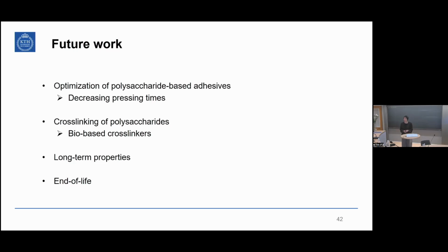For future work, it would be interesting to optimize these polysaccharide-based adhesives. They show promising results, but for larger scale application, the formulation needs to be optimized so we can decrease the pressing time. For example, in particle board production, if you use polysaccharides with lower molecular weights, they are more soluble, so less water is needed for their hydration, which would decrease the pressing time.